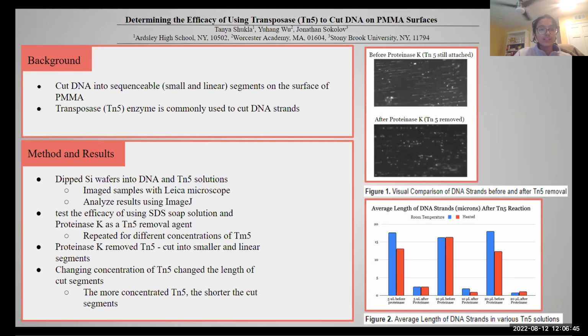So our objective was to cut DNA into sequenceable segments on a PMMA surface with transposase, more specifically TN5, with the hope of holding its orientation. Transposase is an enzyme used to cut DNA, therefore it was used as our cutting agent. Our methods consisted of creating the TN5 and DNA solutions, dipping them onto silicon wafer spun cast with PMMA, imaging our samples, removing the TN5, imaging them again, and then analyzing our results with ImageJ.